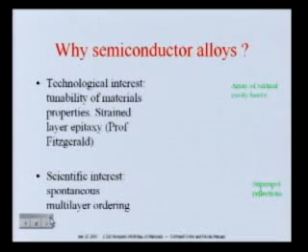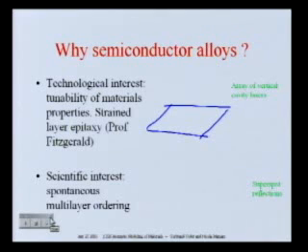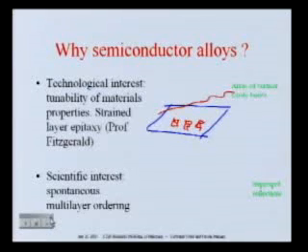In particular, Professor Fitzgerald works a lot on some of these alloys to actually improve mobility of the carriers. And I had here a beautiful picture of an array of vertical cavity lasers in which a number of vertical pillars were grown on a surface with a composition gradient for their active layer. So what you achieve on a single breadboard is a very high density of emitting lasers, and each one emits at a slightly different wavelength because the band gap is tuned by the compositional gradient in that array.